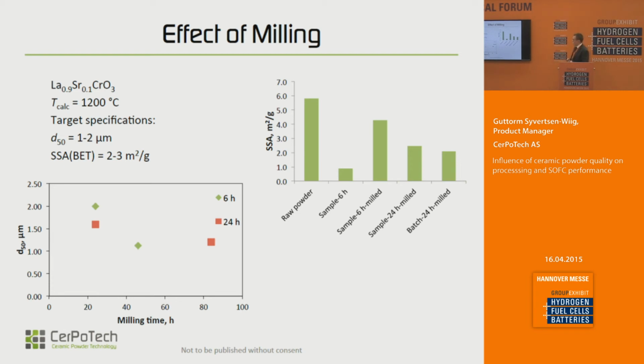So this is a case study on lanthanum chromite doped with strontium, where we had some target specifications of D50, the average particle size, between 1 and 2 micrometers, and the specific surface area measured by BET was supposed to be 2 to 3 square meters per gram. And then we used both different calcination temperatures and different milling times, showing that we actually achieved these numbers quite well.